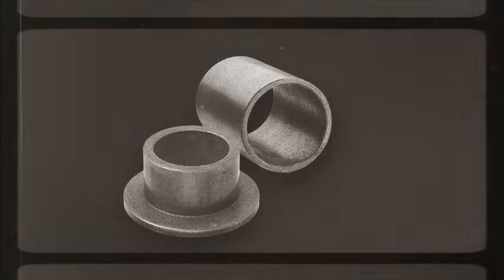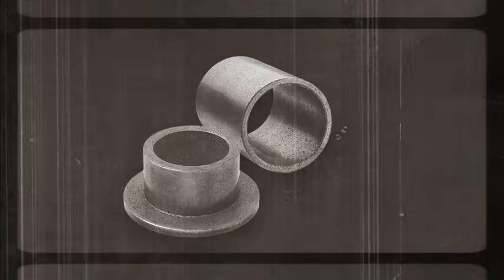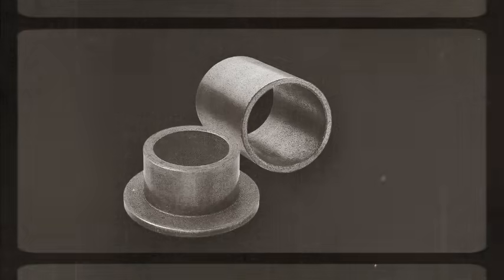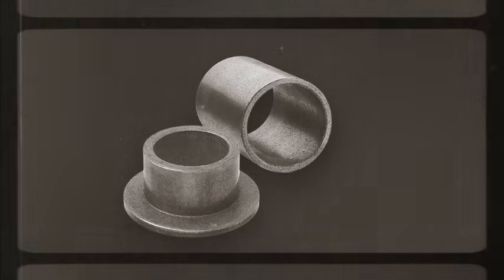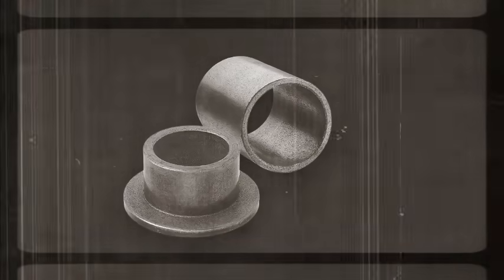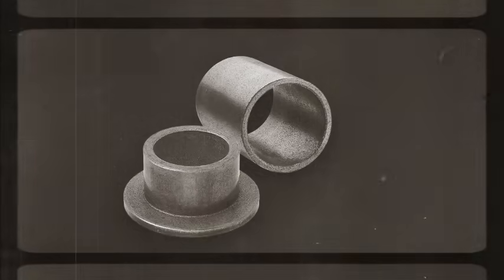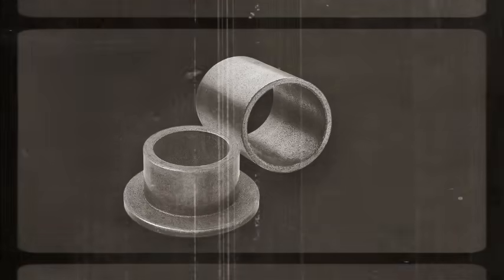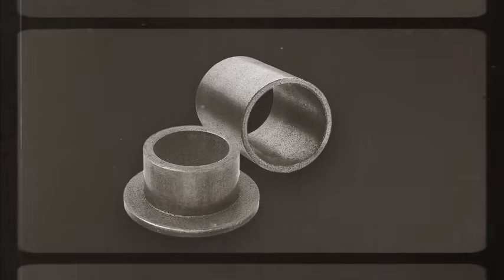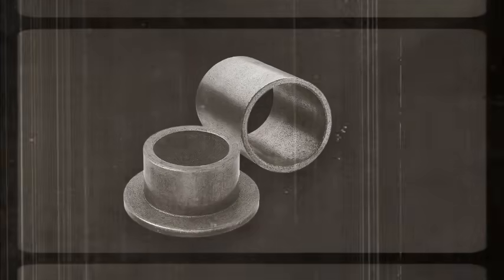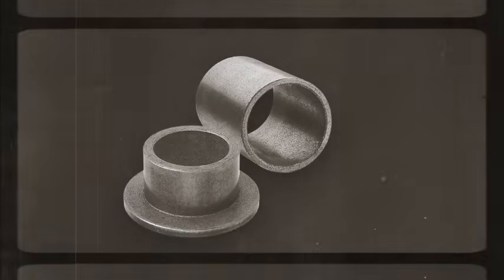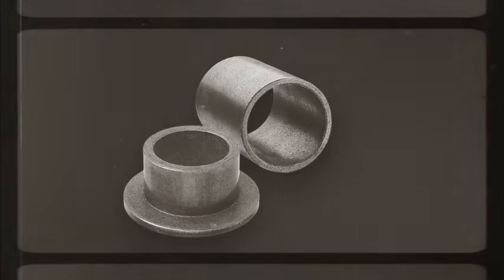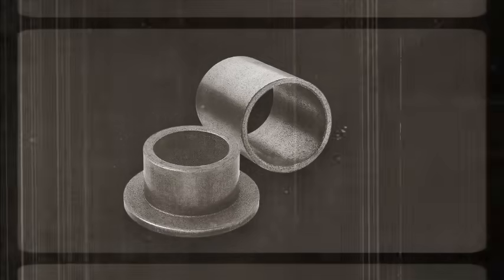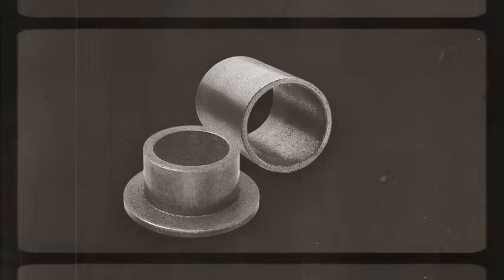General Motors had attempted adding graphite to copper tin powder to create self-lubricating bearings in the early 1920s. The graphite, naturally slippery like pencil lead, was supposed to provide lubrication, but the bearings failed. They were too porous, too weak, or the graphite didn't provide adequate lubrication under high loads. Sherwood and Calkins took a different approach. Instead of relying on solid graphite for lubrication, they would create porous metal that could hold liquid oil internally.